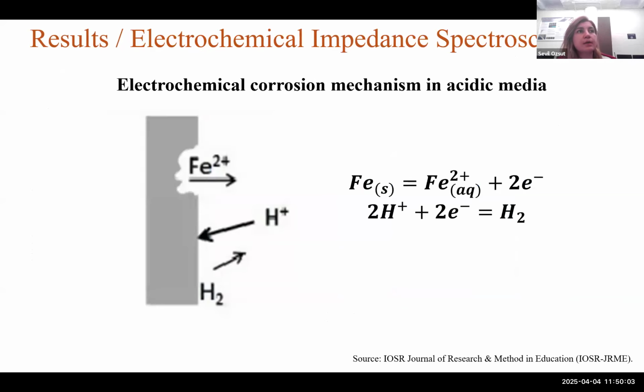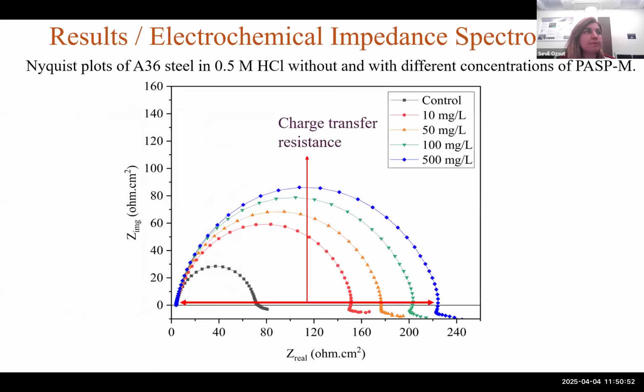This is the electrochemical corrosion mechanism in acidic media for metals. Corrosion is fundamentally an electrochemical reaction involving electron transfer from iron to oxidizing agents, and these agents in acidic media are the hydrogen ions. So the corrosion rate depends on how these electrons are transferred at the metal interface. If we can block or significantly reduce that charge transfer, we can say there is a decrease in the corrosion rate.